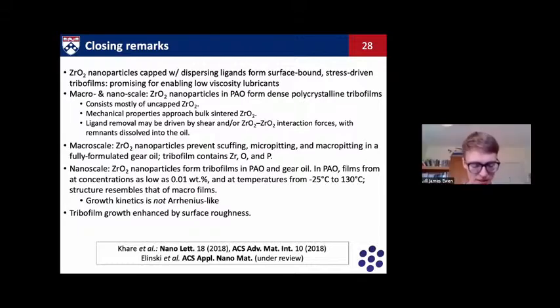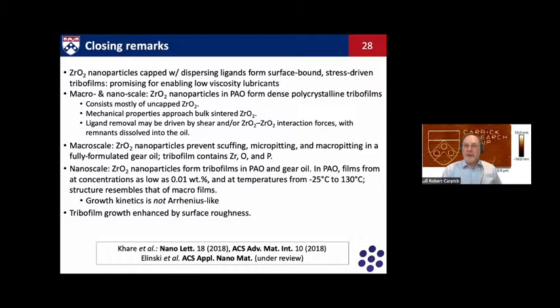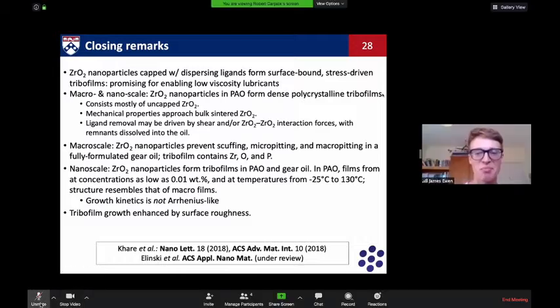Thanks. And another quick one from Ramin Agabebe. Can we distinguish between the contributions of shear and normal stresses from a chemistry viewpoint inside the contact? Well, from the experimental point of view, obviously we get the friction we get. But what I only touched on briefly was we measure the friction while we're doing the experiment. And what we haven't looked at closely yet, we're in the middle of looking at, is how does the friction vary throughout the experiment? I showed you a couple plots of that. How does that correlate with growth? So looking at different loads, and how the friction changes is one way to look at that. But I think we need help from theory. We need simulations that can help disentangle what components of the stress tensor end up affecting the chemistry. And that, I think, is an important challenge for people in the modeling community that we would love to see addressed.